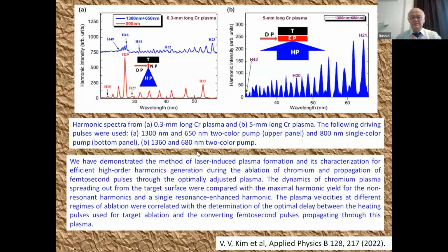Thus, we have demonstrated the method of laser-induced plasma formation and its characterization for efficient high-order harmonic generation. In the case of chromium, we observed the appearance of a resonance harmonic, which is unusual for high-order harmonic generation and cannot be observed in the case of gases; it is a feature of this material. Thus, we have shown that this method creates not only a source of extreme ultraviolet photons, but can also be used for material science in the extreme ultraviolet range.